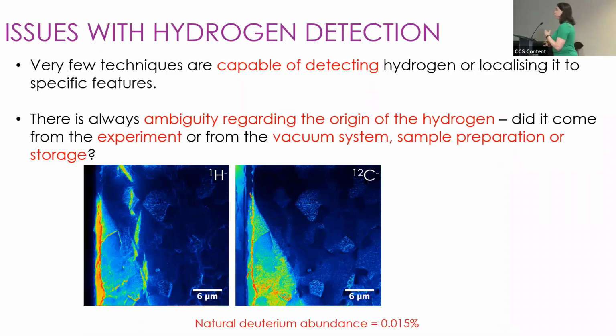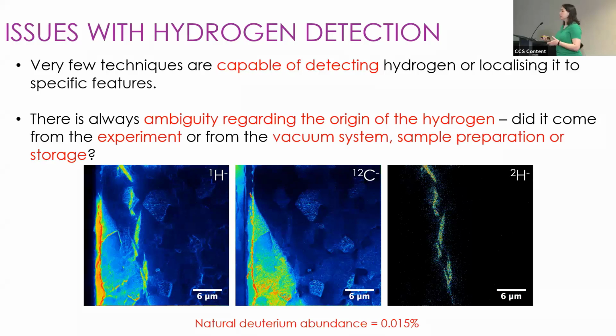We use deuterium. So we artificially introduce deuterium in our charging process, and we map that instead. And we assume that hydrogen and deuterium behave the same way in the microstructure. The reason we like to use deuterium is that it has a very low natural abundance, only 0.015%. So pretty much any deuterium we detect in the NanoSIMS must have come from our experiment. We have introduced it. So if we look at the deuterium map now, you can see that that particularly smudgy feature over here has completely disappeared. We're just left with the hydrides, which must have formed from hydrogen we introduced during our experiment.